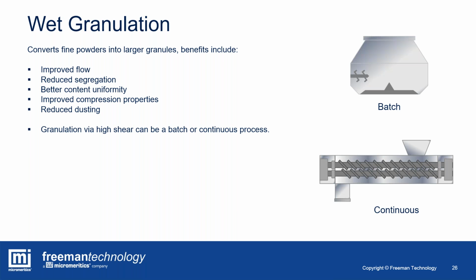It can be a batch or a continuous process. You can see a typical, very simple sketch of the batch process on the top right here. You have an impeller on the bottom of the granulator bowl. You fill your blend and your measured components into the bowl. You have a high-speed chopper, and what's not shown actually is the addition of water as a binder. And this process then continues to make a batch wet granulation.